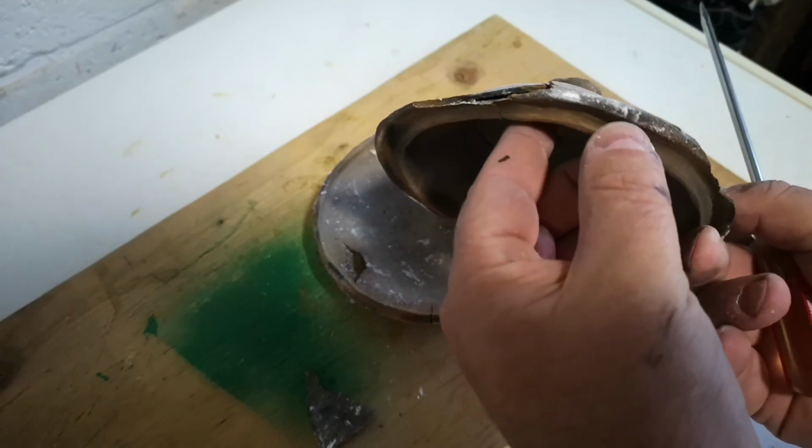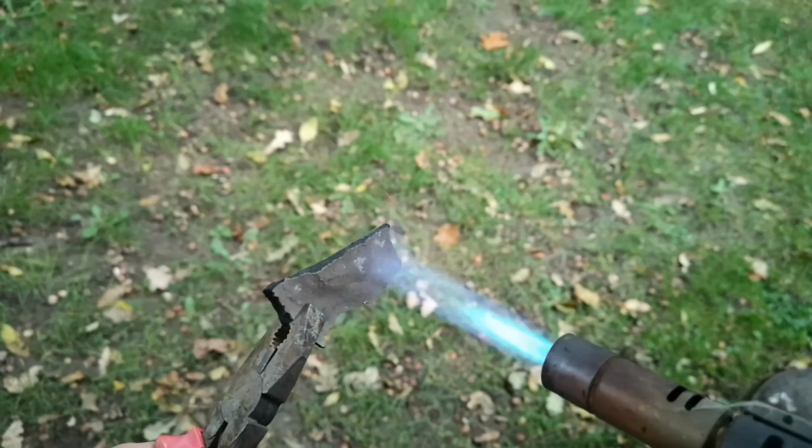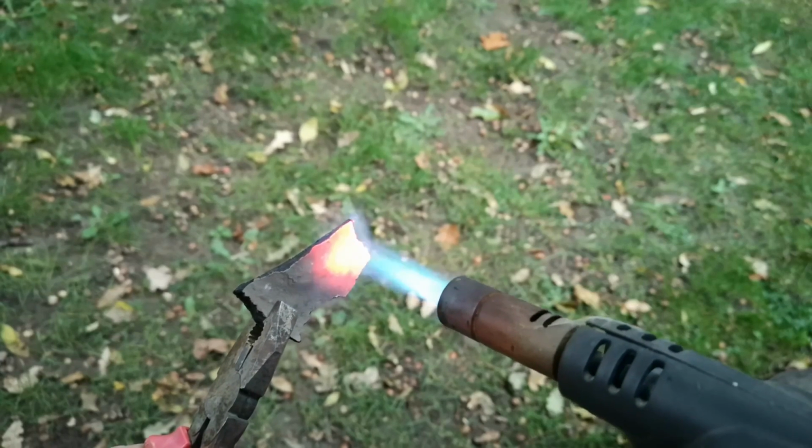I don't think plain thermal shock was to blame. In fact, the remaining low-fired sherds can be heated quite suddenly and unevenly with my blowtorch, and, against my expectations, they don't crack or flake at all.